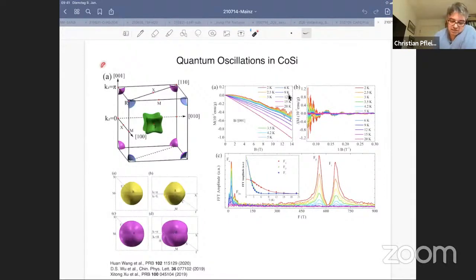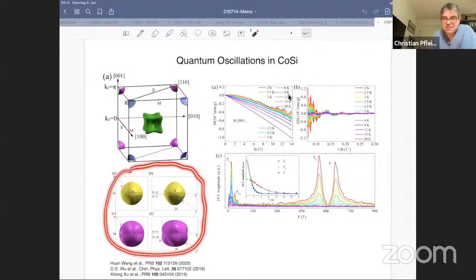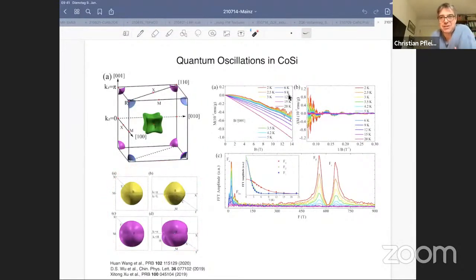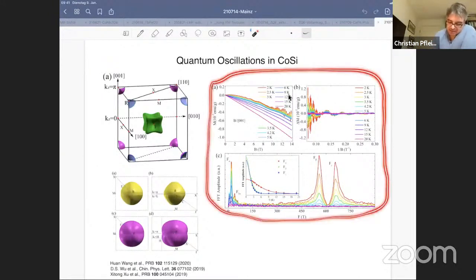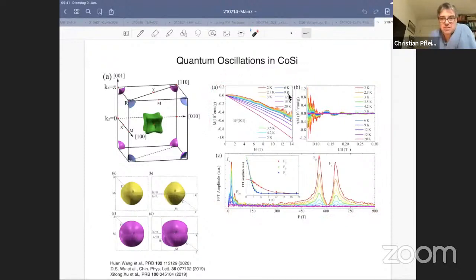So this is in a sense a more conventional way of looking at the Fermi surface of cobalt silicon. So you have a small Fermi surface pocket at the gamma point, and then you have the Fermi surface pockets at the R point. And we're particularly interested in these Fermi surface pockets at the R point. They are shown here, right? So depending on whether you believe spin-orbit coupling is important or not important, you have either 2 or 4 of them. These are typical data that were recorded and reported in these studies. And again, I will return to this later